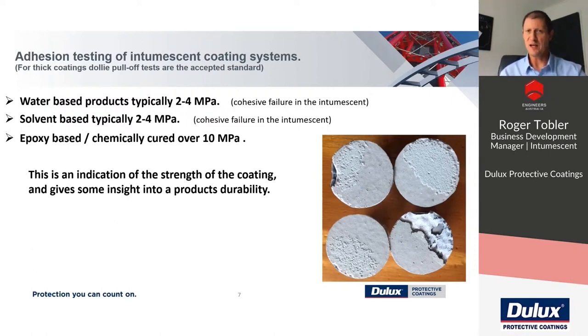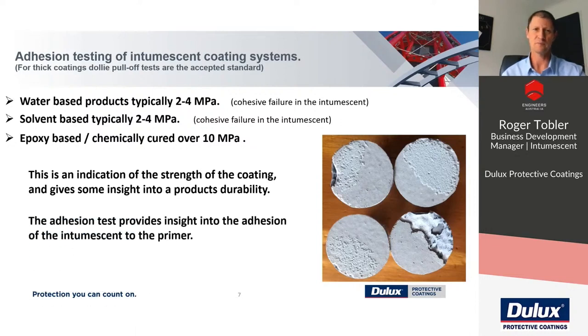This testing gives us an indication of the strength of a coating, and that strength is giving you some indication of the durability that you can expect from a product. The adhesion test is also telling you a little bit about if the intumescent sticks to the primer and if the top coat sticks to the intumescent.